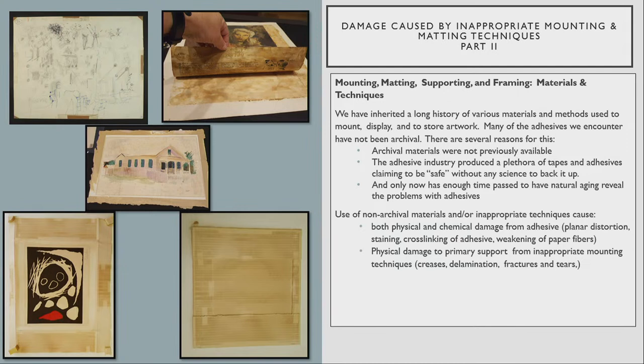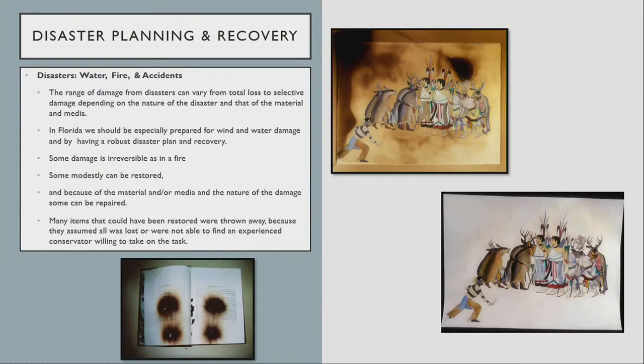This Calder was folded, so you can see on the right. And then you can see those lines. What do you think it was up against? Cardboard, right? Those are the very lines you see of the cardboard. And the reason you see that rippling is because the cardboard ripples and the points of contact between the cardboard peak is what stained it, and then the cardboard, the sort of valley of it, didn't make contact, and so it just transfers that acidity. Acidity moves, it just doesn't stay where it is. If you take something that's non-acidic, an archival paper, put it next to an acidic item, that archival paper will absorb that acidity because acidity migrates. It has a life of its own.